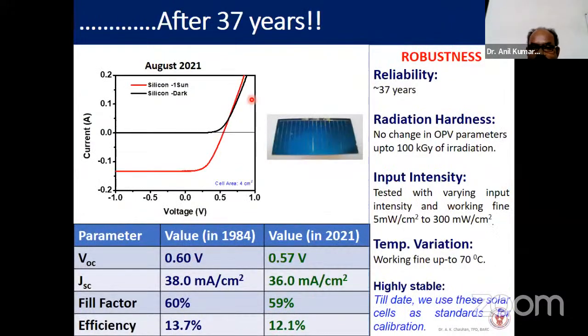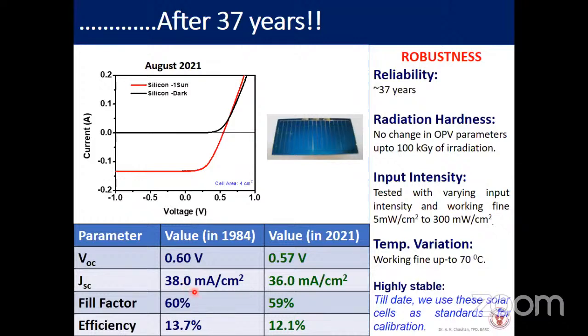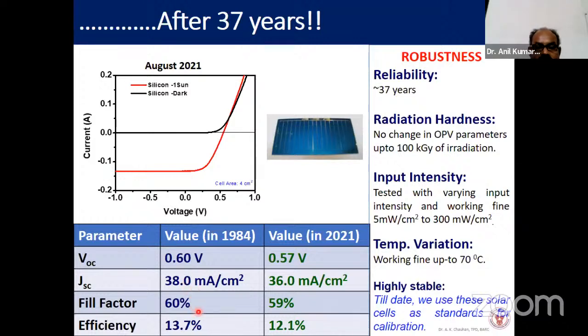To test the robustness, this is the same solar cell on which I did the measurement. These values, which were from 1984, I have taken from the technology transfer document. On average, the open circuit voltage was about 0.6 volts, short circuit current about 38 milliampere per centimeter square, fill factor around this, and efficiency at that time was around 13.7. This batch had 13.7 efficiency, and if I measure the same thing now, it comes to about 0.57, 36.0. So over a period of 37 years, you can say these are highly reliable solar cells which were developed by us.